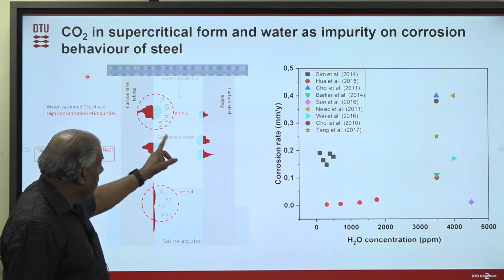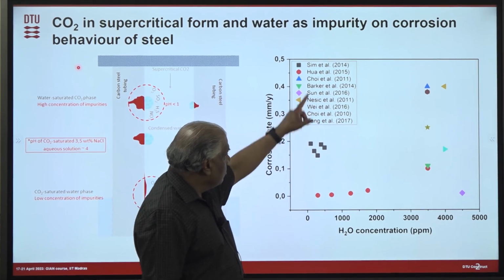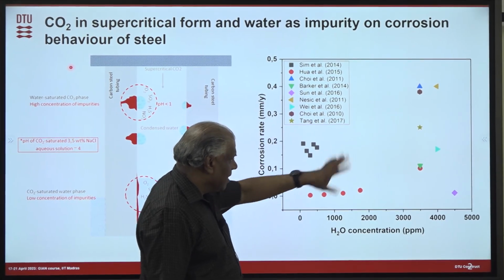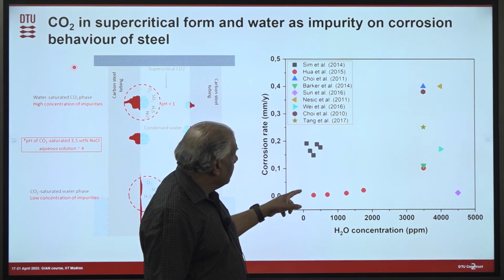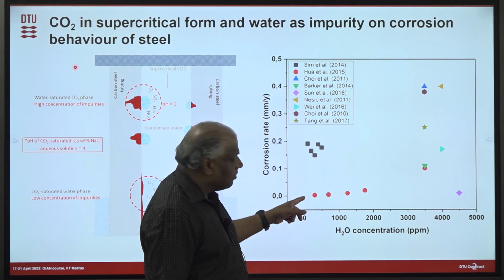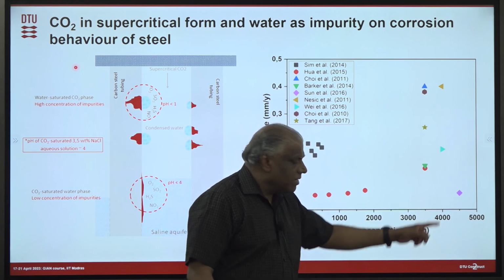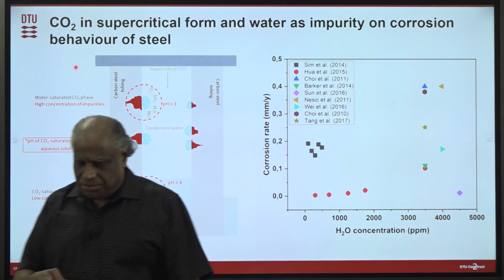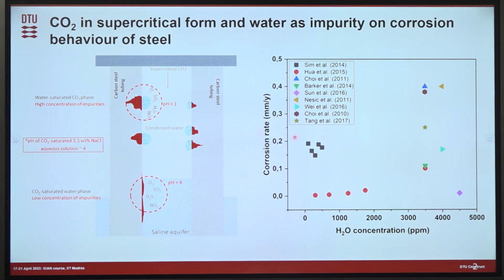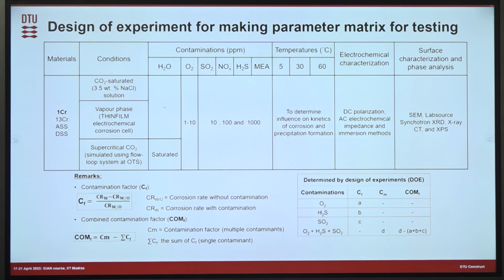So here we can see the importance of this. People have done work on this. We collected this data from the literature and we are trying to plot it. You can see that different people have done this work, looking at how the corrosion rate changes with an increase in the amount of water in the CO2. You can see that it goes up with increasing moisture content. Understandable, right? Because that moisture content makes these gases dissolve, and that way you can have the corrosion problem. So that's what we are trying to look at.